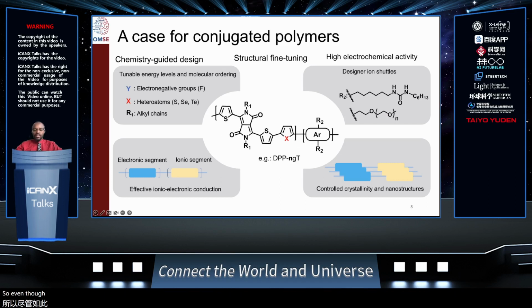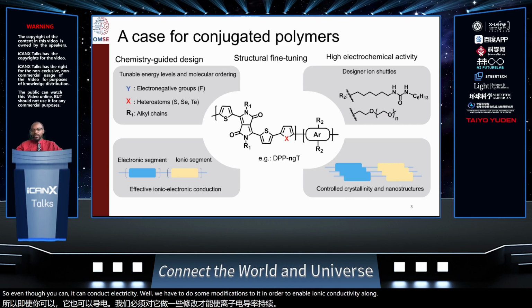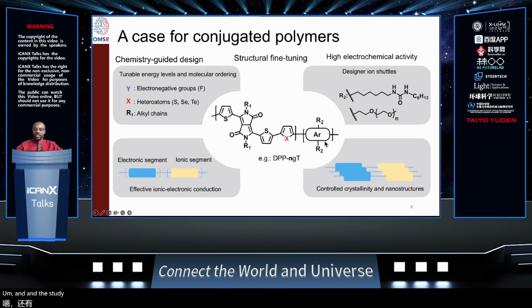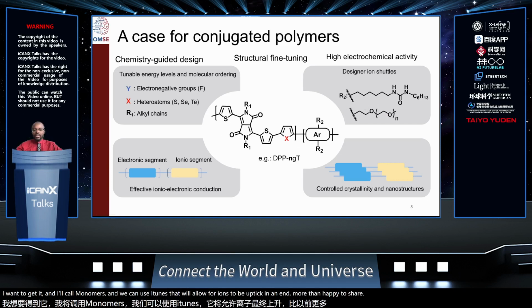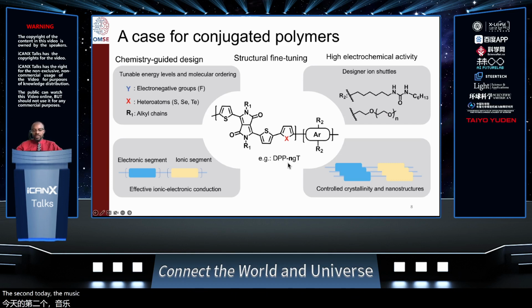So even though it can conduct electrons very well, we have to do some modifications to it in order to actually enable ionic conductivity along its backbone. So in this example that I will share today, we decided to start with this well-known electron conductor, and we started modifying it by making copolymers using a functionalized aryl group, a conjugated comonomer. And we can use side chains that will allow for ions to be uptaken. I'm more than happy to share more of the details on the structure later in our discussion. But for the sake of today, let me use a shortened version where I'll call it DPP-nG-T.